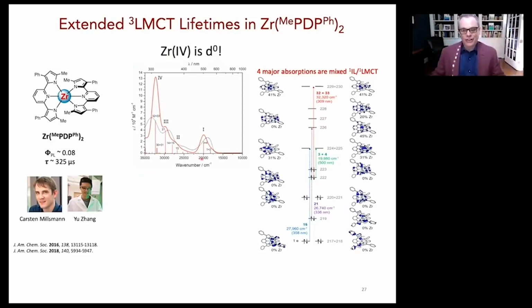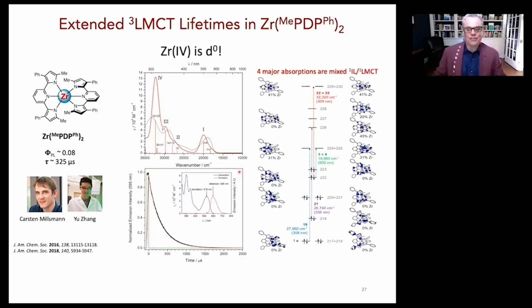But what's really interesting is it has a very high extinction coefficient, almost 30,000, right in the visible, a little above 500 nanometers. And what's amazing about this compound is this interesting admixture when looking at the frontier orbitals. There's a lot of ligand to metal charge transfer character, and there's a lot of ligand centered character. So this sets you up in a really interesting way to think about mixing in ligand triplet with this. And ultimately that gives you a 325 microsecond room temperature lifetime. That's crazy in this field.